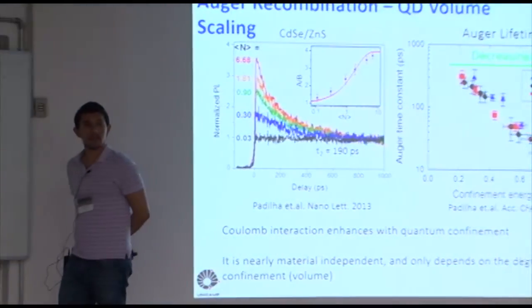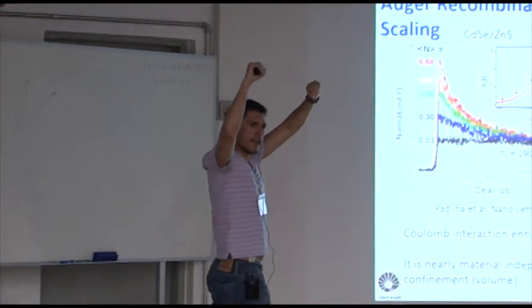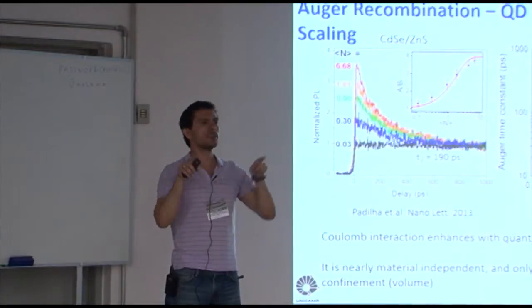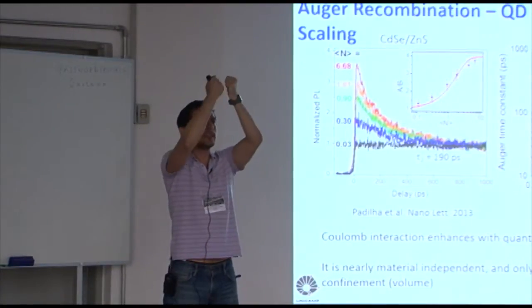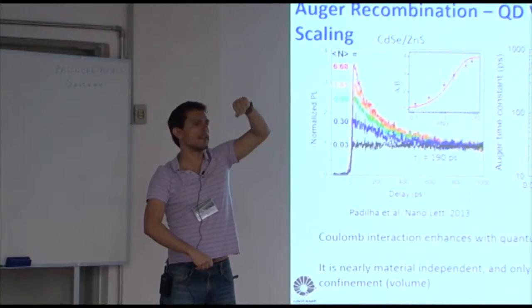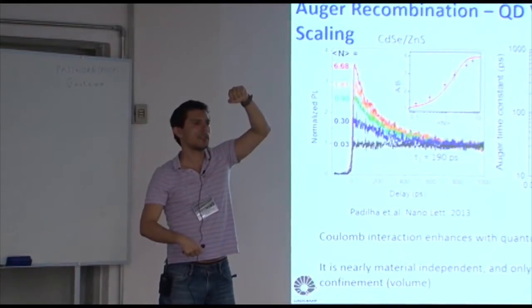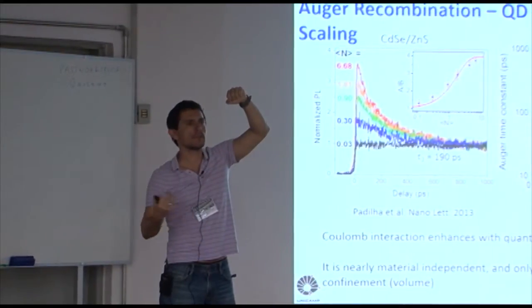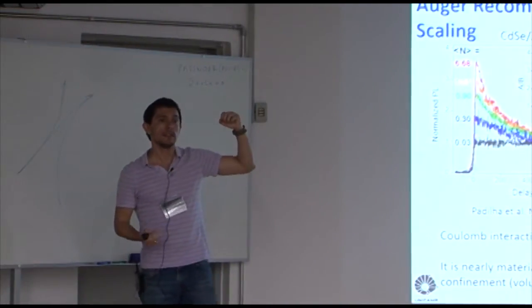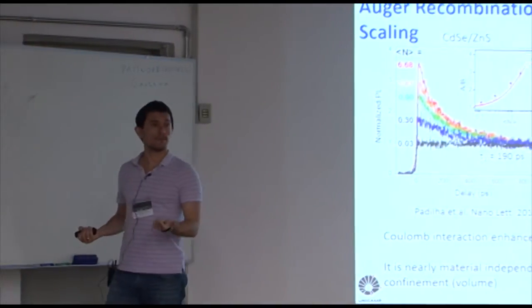This fast component is basically this exciton seeing this exciton. And instead of they come down together and emit two photons, no, they hit each other, transfer energy, this guy comes down, this guy stays there, and this guy doesn't emit a photon. So we waste a photon. This photon is useless. Okay? So it is very fast. Why? Because they're pretty close.